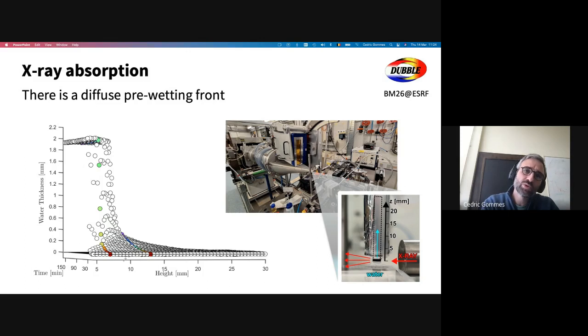And what you're seeing here is not yet the small angular scattering patterns, but it's just the absorption. Right? Basically, we measure how many X-rays get through, and based on how many X-rays get through, we know how much water there is as a function of height for different times. Yeah? And the interesting thing is that you see we have this two-step process. So this sharp step here corresponds to the filling of the mesopores. So water arrives in the mesopores, but it's preceded by the diffuse step here, which is not completely clear what it is. Yeah?